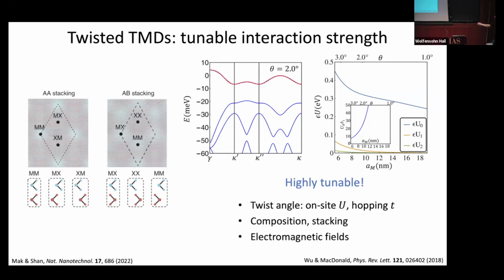as you change the twist angle, you change the effective separation, the Moiré wavelength between these, you change the size of this Moiré Brillouin zone or Moiré real space Moiré texture. And what that does is it modifies the effective on-site interaction U, effective hopping T.